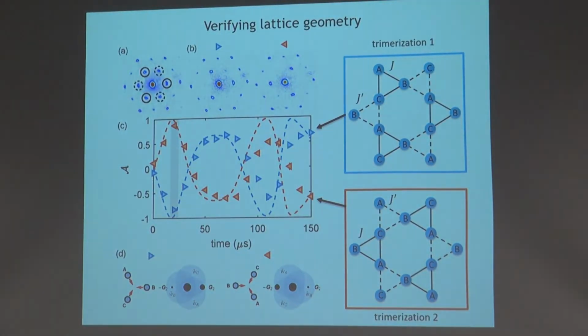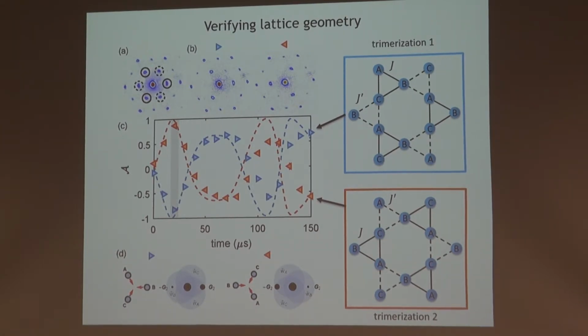So this is what the diffraction patterns look like after this sort of perturbation of the lattice. And if you focus in particular on the first order diffraction peaks, you see that the atoms diffracting out of one of these perturbed lattices have a spatial inversion asymmetry. So let's say these 3 sites are largely occupied, which is the opposite of what we get when we start the atoms in the opposite trimerization. So we can dynamically, through this method, confirm when it is we've produced one trimerized Kagome lattice or a different trimerized Kagome lattice.